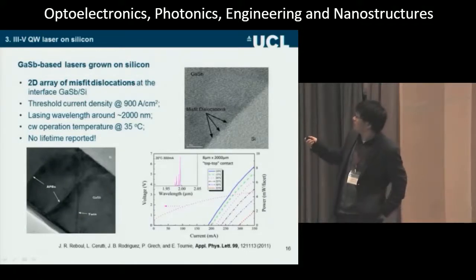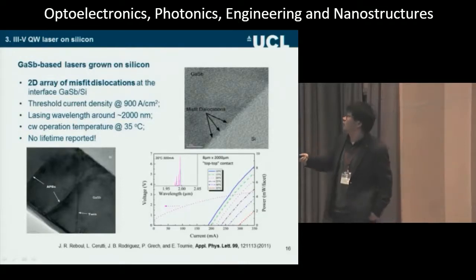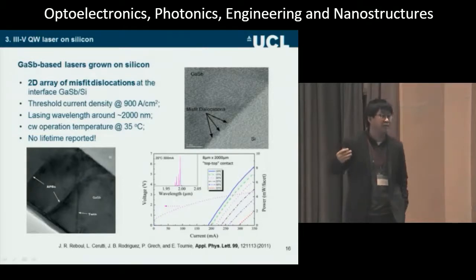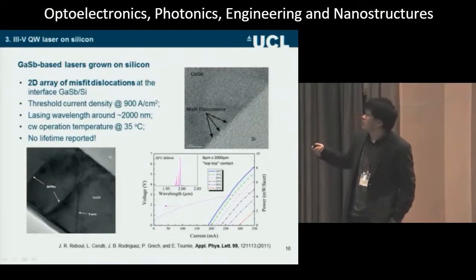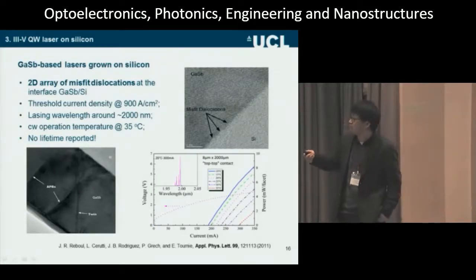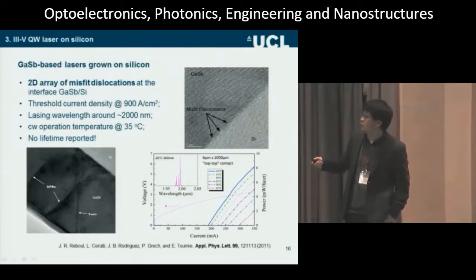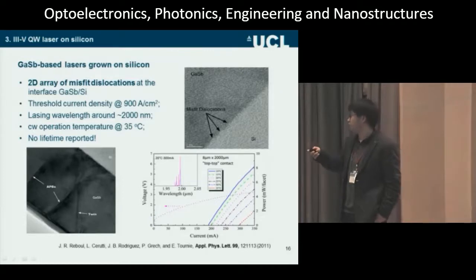If you grow gallium antimonide on a very hard silicon substrate, you can have misfit dislocations mainly at the interface. After that, you can have good quality gallium arsenide on top. You build up a laser on that. But even like this, it only works CW up to 35 degrees, and they never reported a lifetime. You also get twins and threading dislocations in your gallium arsenide material.